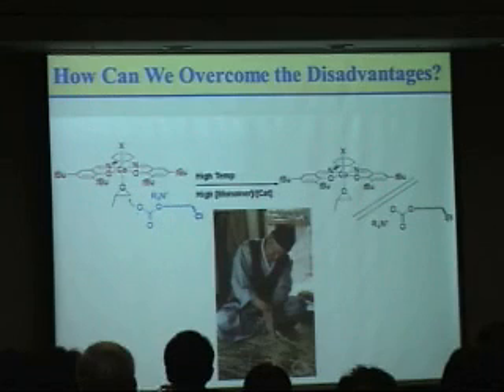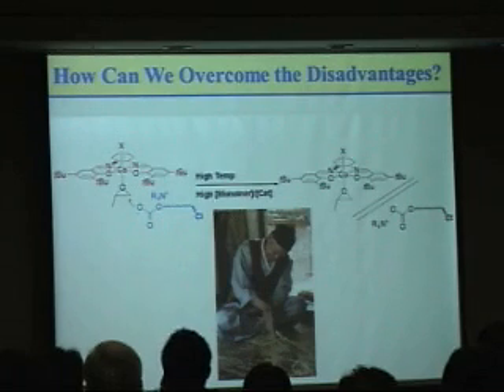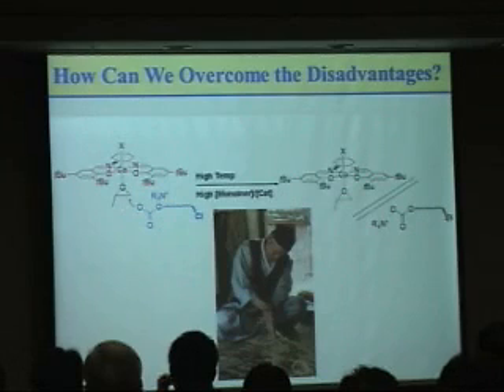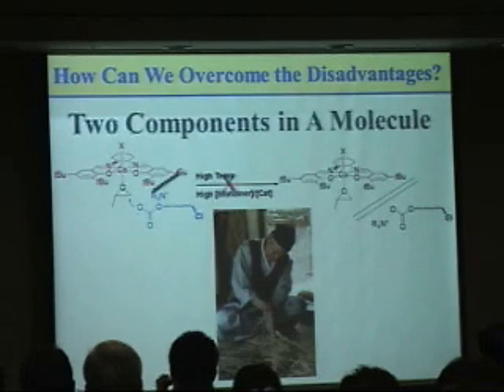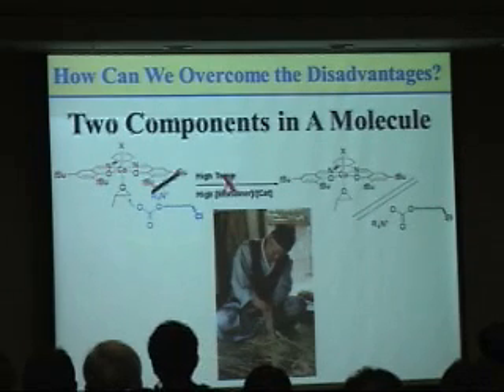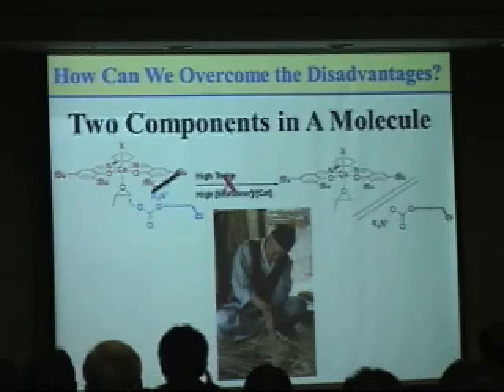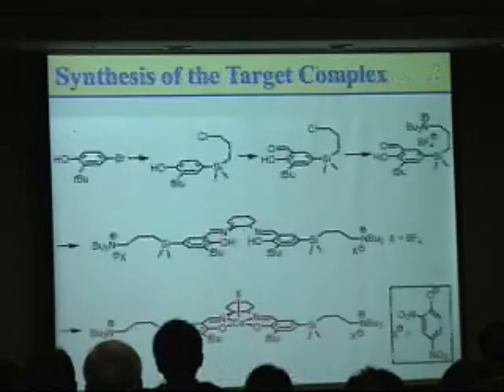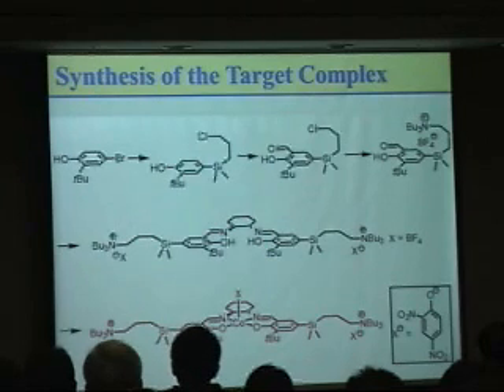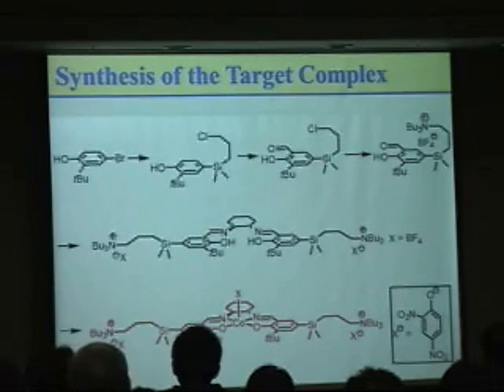So I devised a strategy to overcome the disadvantage. The problem is the very low chance of the two components meeting each other, especially at a high temperature and when we add a very small amount of catalyst. So in order to prevent this kind of dissociation, the concept is very simple: connecting the two components. By connecting the two components situated in proximity, you will be able to work at a high temperature and a high monomer to catalyst ratio. So I was able to prepare the salen cobalt complex tethered by quaternary ammonium salt by simple organic synthesis.